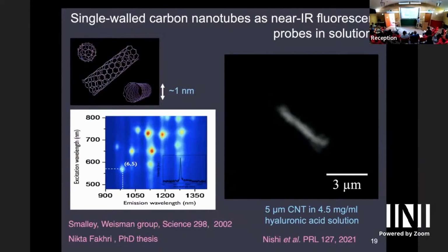And of course, the other advantage is you get information about multiple length scales. With these beads, the radius of the bead is a characteristic length scale, and we can't see anything smaller, we can't probe the response of the system on length scales smaller than the bead size. But here we have modes, and the high modes probe small length scales, and the long modes probe large length scales. So that's an advantage of using these filaments, apart from the fact that they're stealth.